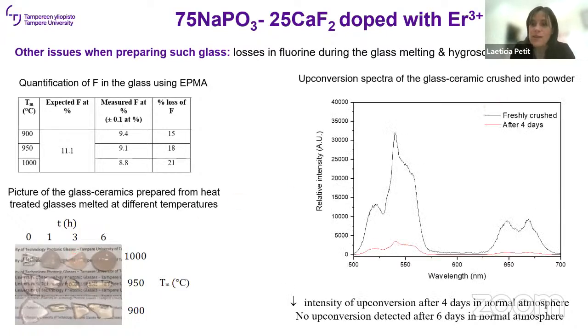The other problem with this glass is that it's a hygroscopic glass. So just to show you why it's an issue, here is the upconversion of the glass in black when it's freshly crushed, because we do the measurement in powder. And in red is after 4 days of storing the glass in normal atmosphere, so not in a desiccator. And we have a huge decrease in the intensity of the upconversion. And after 6 days in normal atmosphere, we could not actually measure the upconversion. So this hygroscopicity of the glass is also an issue here.